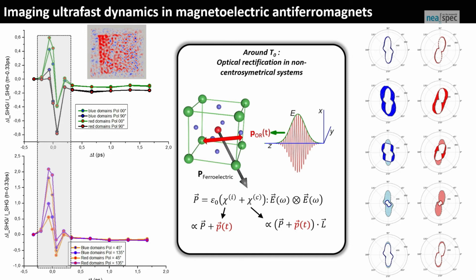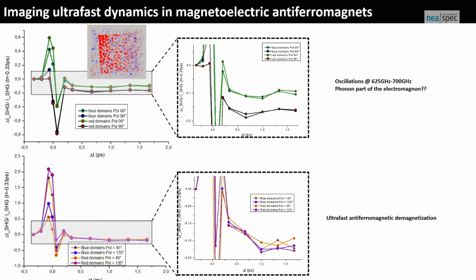So you can distinguish between red and blue domains and look at the time around T0, and what you have here, basically, is some insight on this ultrafast polarization, so you can look at the full angular dependence to have a bit more information. And then if you look at longer times, in the two cases you see the start of an oscillation and an ultrafast decay here.